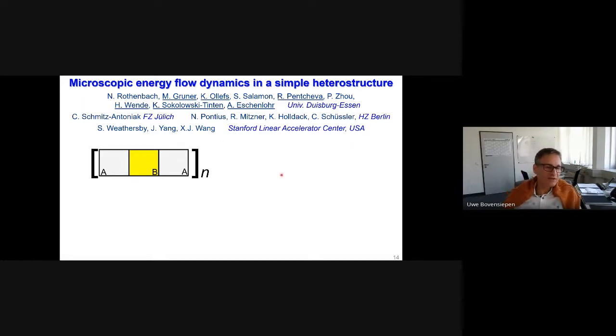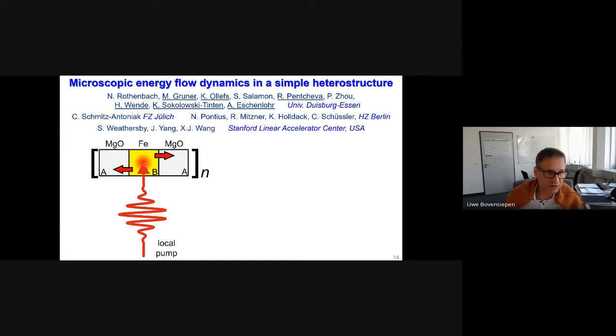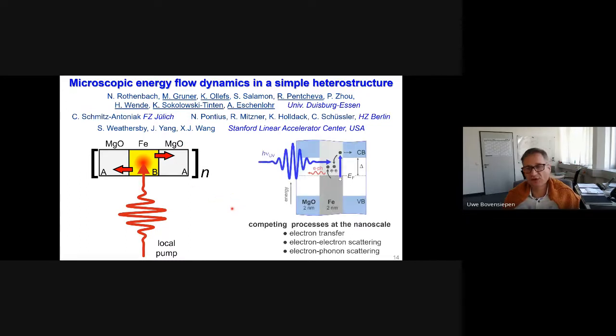So consider a simple heterostructure consisting of constituents A and B, and this is repeated n times. Now we locally excite this by absorbing a femtosecond laser pulse in iron, and then you have this local energy deposited, which is then redistributed through the interfaces into the adjacent material, and this is in our case MgO. So we discuss here iron MgO heterostructures.